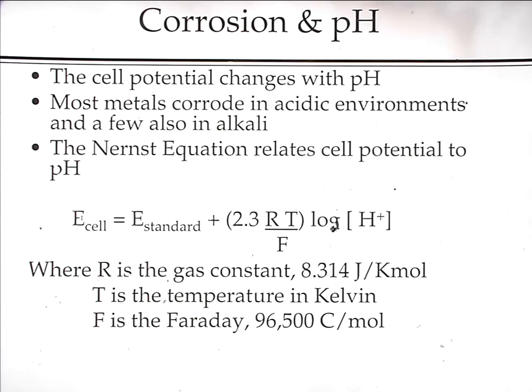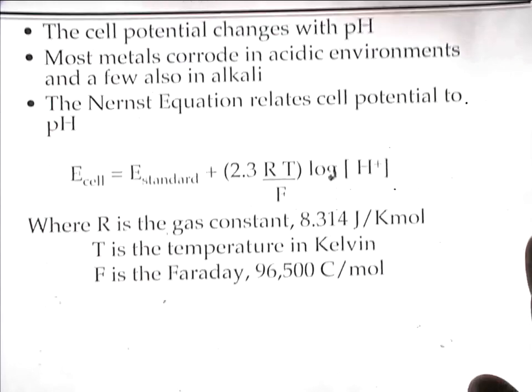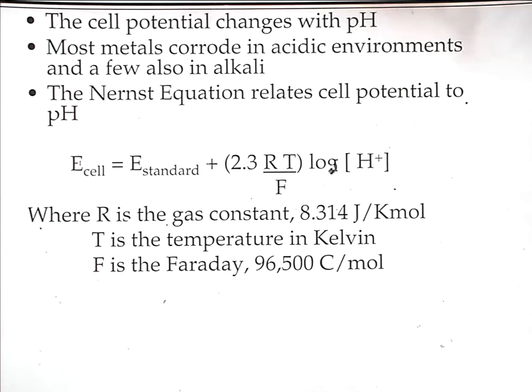The relationship between the standard potentials, which we've got on our EMF scale, and what you see in the real cell can be calculated out using this adjustment for the change in acidity. The negative log of the H+, but of course H+ is a proton, so the real ion in there is the hydronium ion, and that is your acidity. If you calculate out this little bracket here, then that comes out at 59 millivolts per pH unit at room temperature. So for every 1 pH unit change in the acidity, the cell potential is going to move by 59 millivolts.